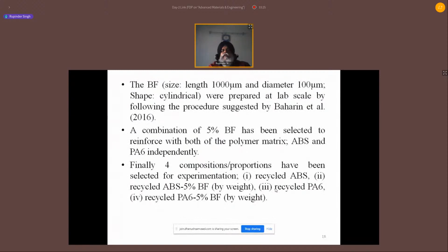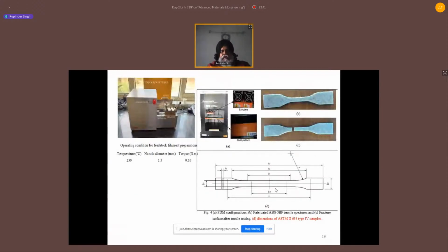So to start with, we selected 5% reinforcement of the banana fiber in different polymer matrices like ABS and PA6, and we tried to print some functional parts. Again, here you see the same twin screw extruder, then the 3D printing, and this is the printing of the tensile coupons as per ASTM D638. Similarly, we explored the flexural coupons using ASTM D790, and similarly the compressive parts also. For processing of the feedstock filament, some standard operating conditions like temperature, nozzle diameter and torque we can control, and depending on the type of reinforcement, I have to do some DOE to manage these input parameters for some typical mechanical properties.